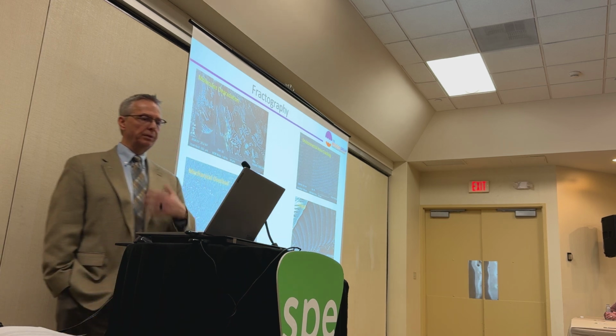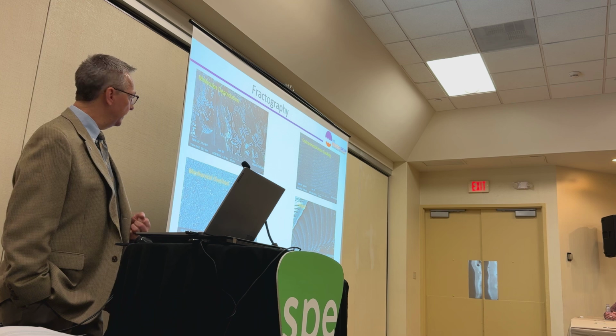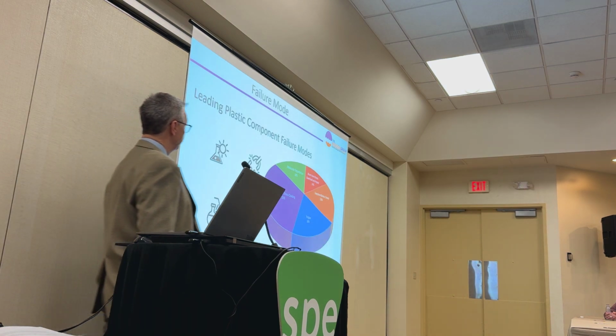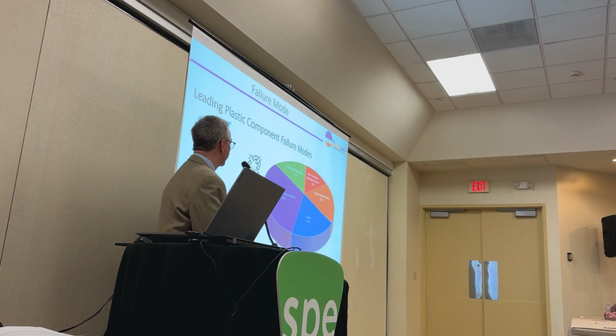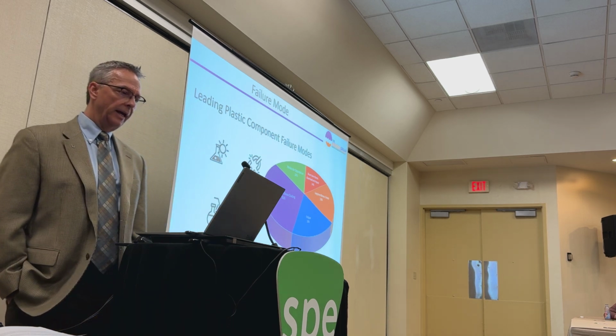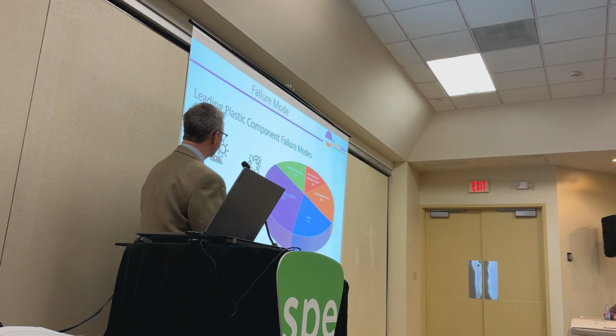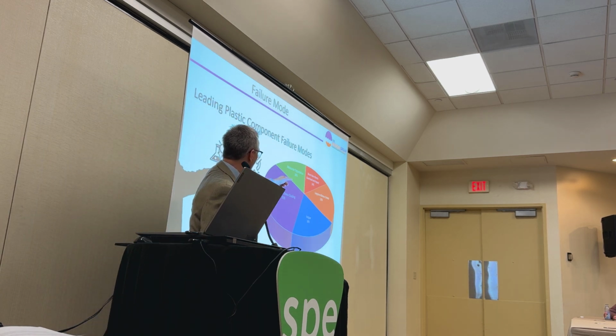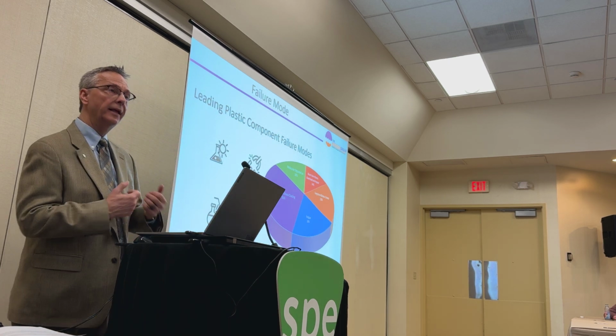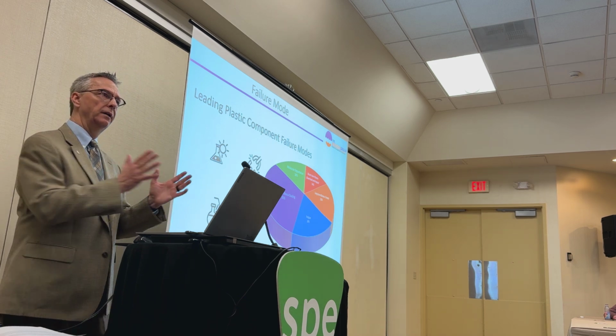And so again, we have a lot of different mechanisms that plastics fail under. There are a variety of them. In fact, in a survey that I conducted, these were the 5 largest plastics failure mechanisms. The largest is environmental stress cracking, that combination of chemical and tensile stress. Then creep is probably number 2, just behind that. Fatigue, molecular degradation, and then impact and overload lumped together as shorter term failure mechanisms. This is what the survey said.